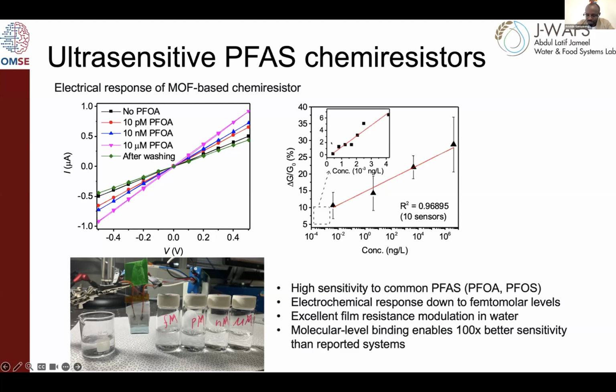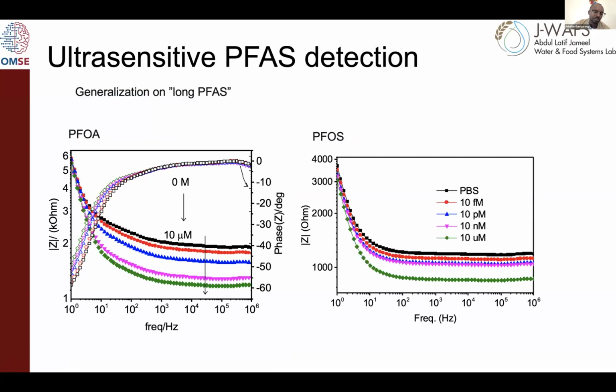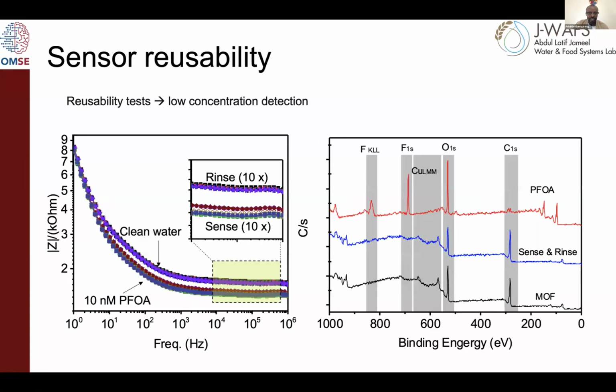I think the graph on my right is actually extracted from these impedance spectroscopy measurements, because these are more sensitive as we go to much lower concentrations. Here we're using something like a BioLogic electrochemical setup to measure the change in the resistance of the material, where the metal organic framework is a working electrode. And you can see that as we increase the concentration of the PFAS, in this case PFOA and PFOS, we're seeing different responses at different concentrations.